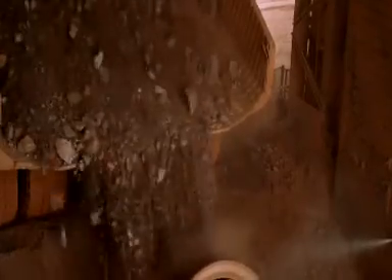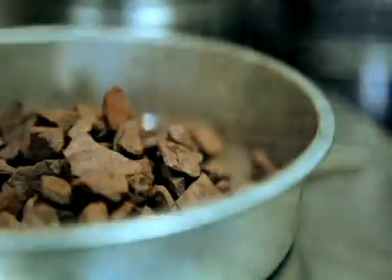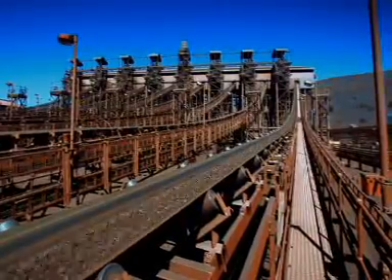Ore from the pit is crushed in primary, secondary, and tertiary crushers. This is to ensure that the maximum size is not greater than customer requirements. It is then washed and screened. This removes fine particles containing impurities and splits the ore into the different product sizes. Material that is not of a high enough quality after the crushing and screening is sent to either a jig or DMS plant to remove remaining waste material. Both plants use the density difference between iron ore and waste material to extract the good quality iron ore.